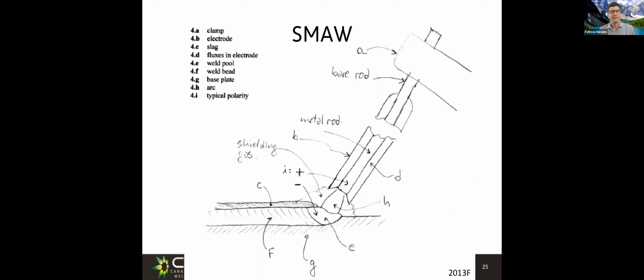But I left it last. And the reason I left it last is because in this case we have all the complexities plus a new one. Now we are melting the electrode, we're protecting the electrode with a flux, and now the process doesn't even run in steady state. We're not unspooling a wire like in MIG, or like in subarc welding or flux core. We have a stick and we start burning the stick until we finish. And then we change and we start a new one.